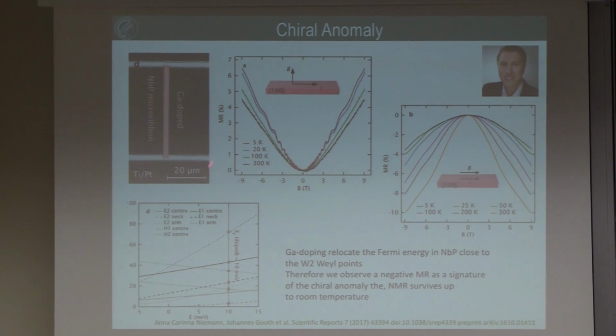By shipping this micron ribbon, he accidentally doped the sample with gallium, which you normally don't like. Our referees didn't like it too, but luckily now we were even 5 milli-eV below the Fermi energy with this, and we could easily assign it, because even the micron ribbon shows very nice quantum oscillation.